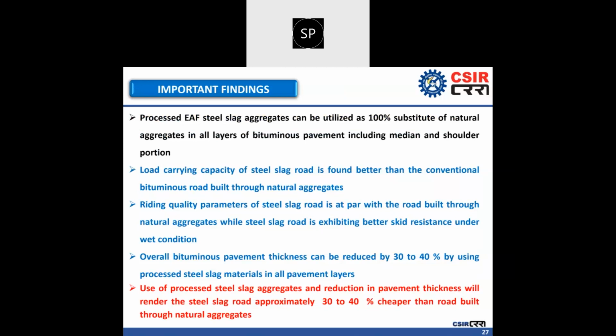Riding quality parameter of steel slag road, as I have shown you in the previous slide, is at par with the road built through natural aggregate, while steel slag road is exhibiting better skid resistance under wet conditions. By virtue of the rough surface texture, the steel slag road wearing course offers better skid resistance under wet condition in comparison to the wearing course built through natural aggregate. Overall bituminous pavement thickness can be reduced by 30 to 40% by using the processed steel slag material in all pavement layers. This is one of the major scientific achievements which can basically enhance the utilization.